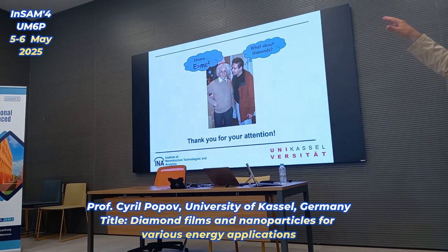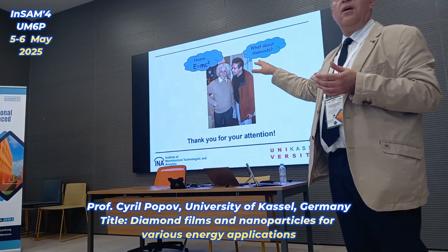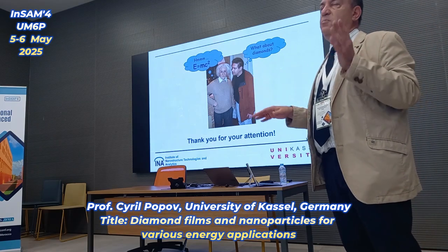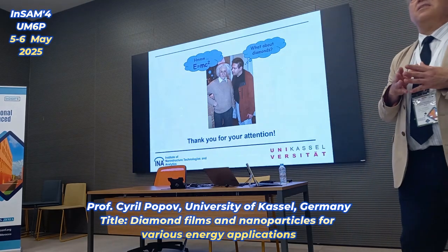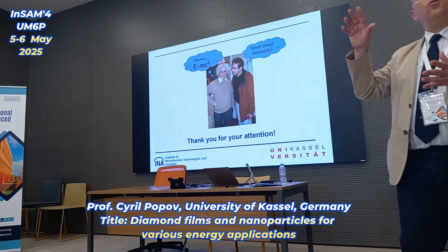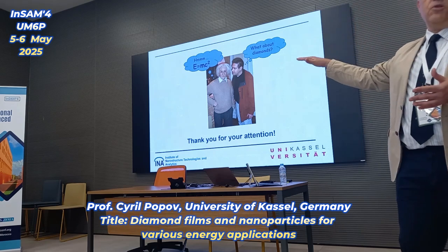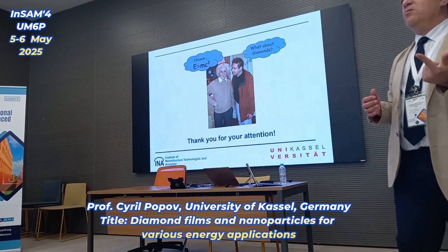That's why you need to select parameters according to the substrate. It is possible to find also glasses. We have deposited ultra-nanocrystalline diamond on glasses, but they're special. They have glass transition temperatures a little bit, let's say 30, 40 degrees higher than the temperature we used. So this is the first. The second depends on the quality.